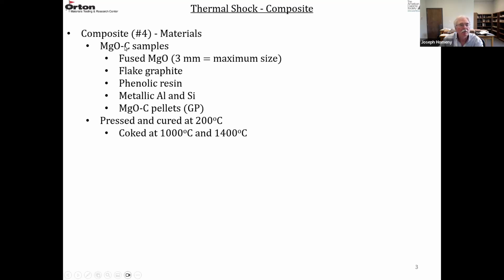And then the actual samples, the MgO carbon samples, were made with, again, fused MgO, and the maximum size was 3 millimeters. Flake graphite, phenolic resin. They added the metallic aluminum and silicon as the antioxidation agents. And then GP, they added the MgO carbon pellets. So these were pressed into samples. Resin was cured at 200, and then they coked the samples at either 1,000 or 1,400 degrees C. And again, coking is just burying these samples in carbon in a sealed container and then heating them up to pyrolyze the resin, convert it to carbon.